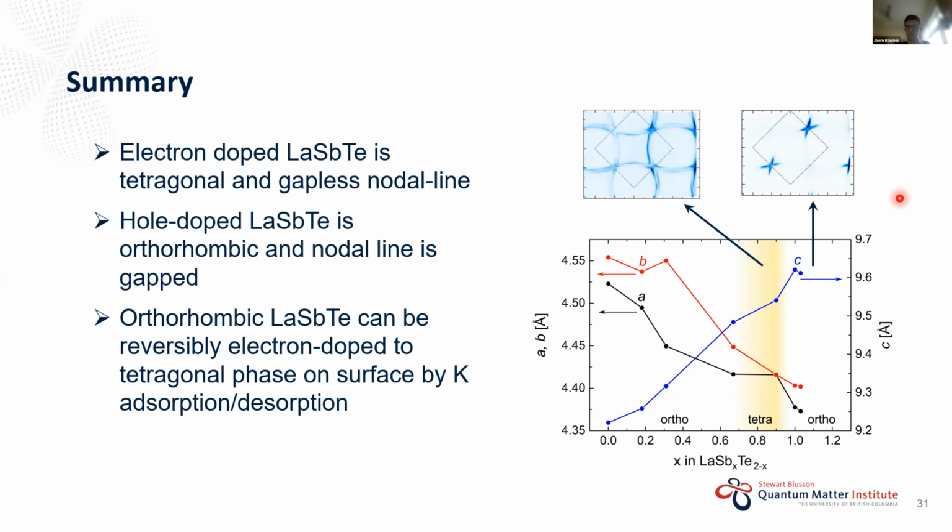So, I'm trying to think about how you can change the orthorhombicity on the surface. Are you thinking about this gap phase as really due to some sort of electronic-driven phase rather than lattice-driven phase? Yes, well, at least our interpretation of this is really electronically driven to gap out these highly nested Fermi surfaces. And then, if you want, the lattice kind of follows this transition, because it seems that really those energy scales are very, very similar to each other. And then small changes can just tip it over into either way.